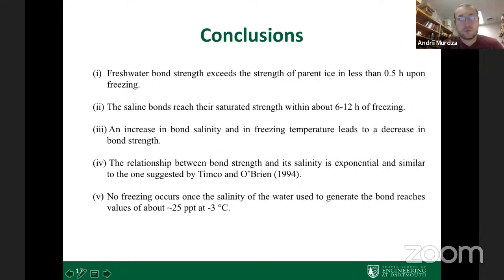So the conclusion of this work is that the strength of the freshwater bond formed in air exceeds the strength of the parent S2 ice in less than half an hour upon freezing. In the case of saline bonds, it takes about 6 to 12, maybe 15 hours to saturate the strength. And then as we increase the salinity or we increase the temperature, the bond strength gets lower.